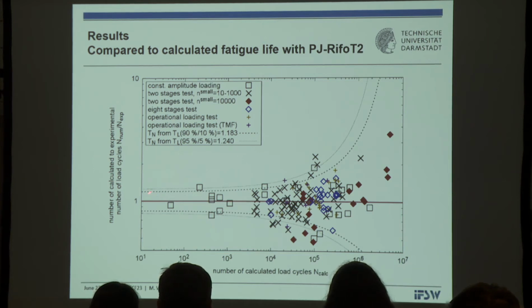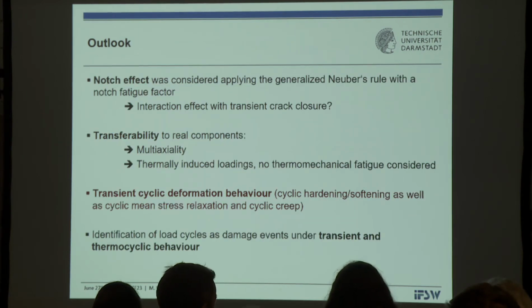And if I plot for these constant amplitude load cases such a difference between number of cycles, numerical and experimental, this means this is scatter around the regression line of our strain life curve. So this is constant amplitude scatter here, and this is variable amplitude loading scatter. And my message is that what is scatter here is scatter in material, and you can only do a better job if you do a probabilistic approach and put everything which has been deterministic here in my approach into some probabilistic framework. So it seems to be everything solved, but this is far away from being so.